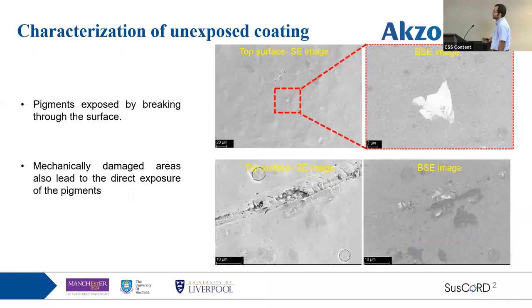The other thing that may lead to the exposure of the pigments to the environment is mechanical damage on the surface. I've observed that a similar change in contrast is seen when you have mechanical damage, which indicates that a pigment is exposed to the environment.